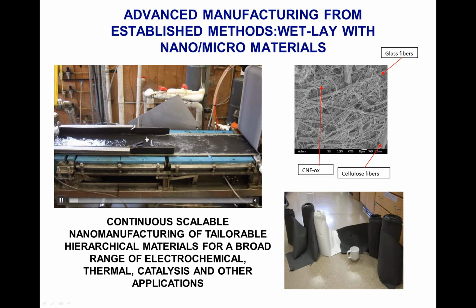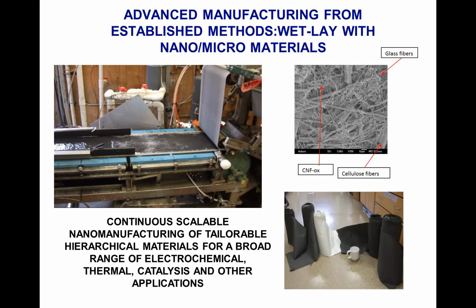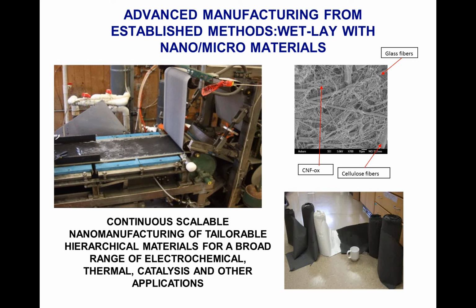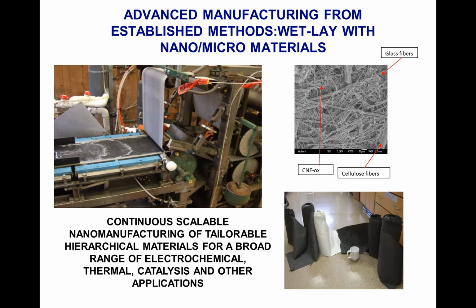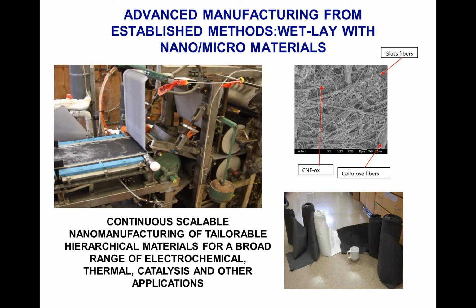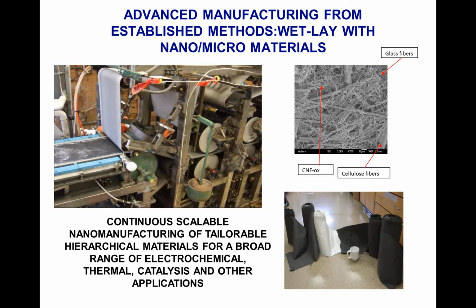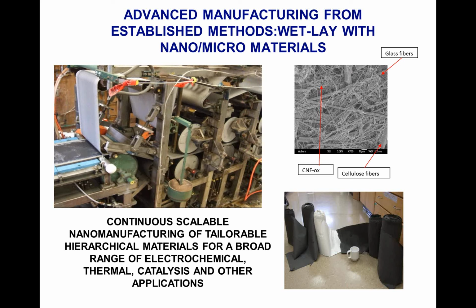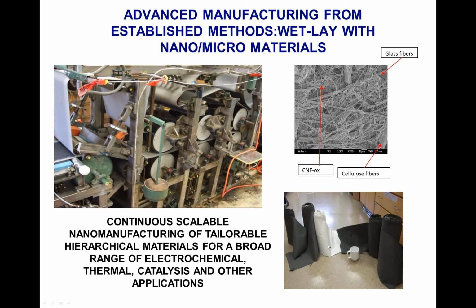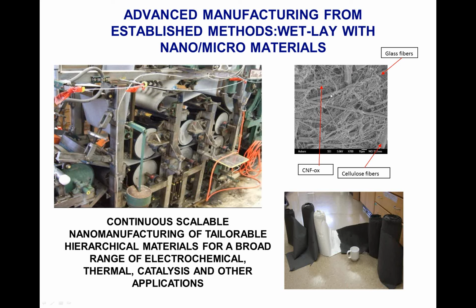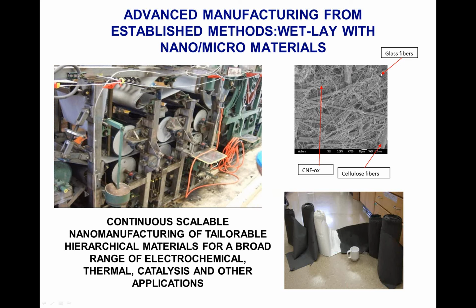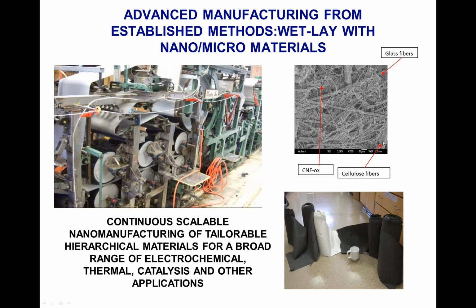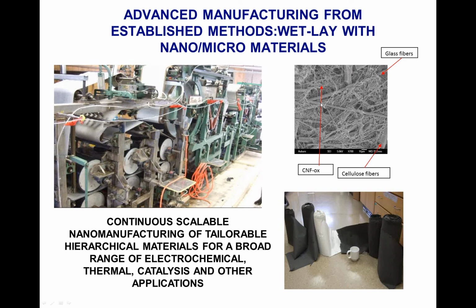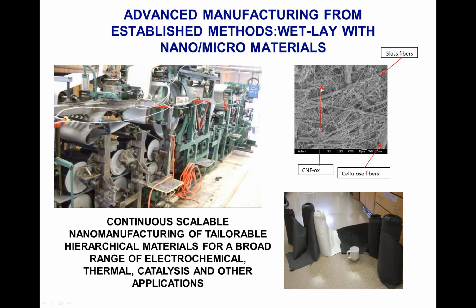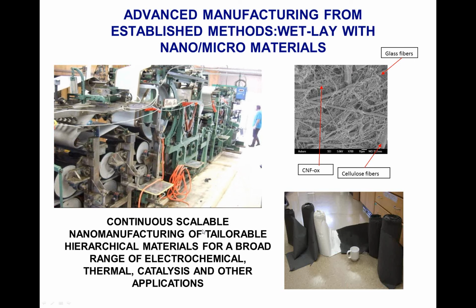What you're seeing here is a combination of cellulose and that vapor-grown carbon fiber, which I mentioned earlier, a nanomaterial that's dispersed and then put on our continuous pilot line paper machine. We actually made several hundred square feet of material using this machine. You can see the materials with the nanomaterials are black, the ones with just the glass fibers are white. This SEM shows that we can make a hierarchical material by using different systems of different size scales: the glass fibers, the cellulose, which could be burnt out to open up porosity, and the vapor-grown carbon nanofibers. We can extend that to other nanomaterials as well for a range of electrochemical, thermal, catalysis, and structural applications.